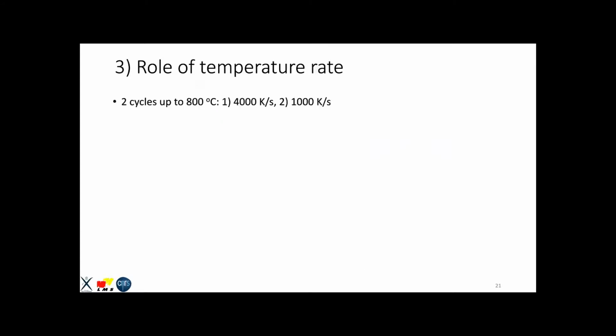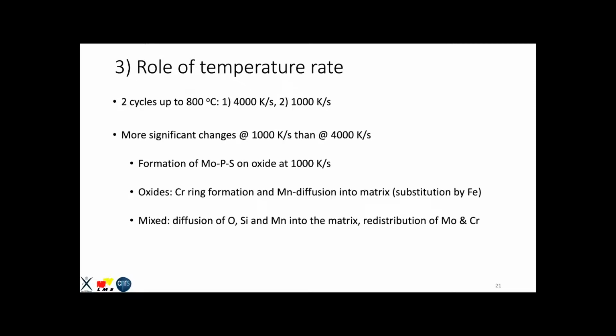Okay, so the next was to study the role of temperature rate. We did 2 cycles up to 800 degrees Celsius on 2 different lamellae. One was at 4000 Kelvin per second, heating and cooling, and the other was 1000 Kelvin per second, heating and cooling. We saw there were more significant changes at 1000 Kelvin per second than at 4000, which makes sense because chemical elemental redistribution is a mass transport process and it takes time. So the more time you give it at the same temperature, the more it will change.